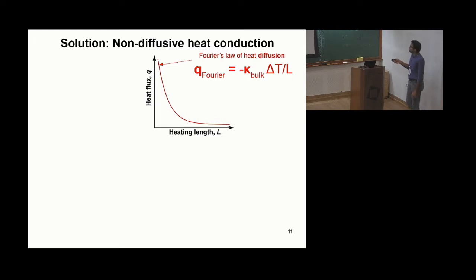An interesting observation you can make is that as L goes to 0, if you make the sample smaller and smaller, Fourier's law predicts that heat flux diverges, which is unphysical, right? In fact, that's the case, because in experiments you typically don't see diverging heat flux.